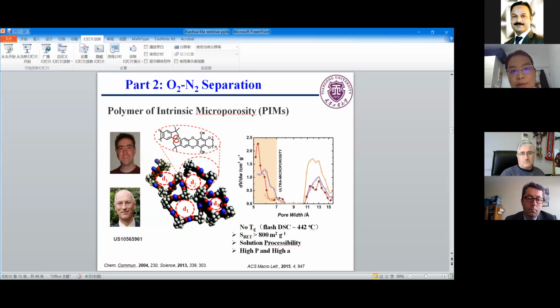This kind of polymer, because of this site of contortion, when it's folded, cannot pack efficiently and creates some pores, with different diameters. That was reflected by the BET-derived pore size distribution, which shows that it contains some ultra-micropores and nanopores. This kind of polymer is very strange in that it has no glass transition temperature.